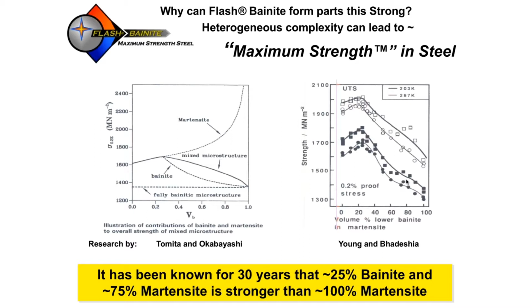Now, on this chart, the strength on the vertical axis is megapascals, of course, and on the horizontal axis is the volume fraction of bainite in a martensite matrix. So what that means is at 0% bainite, 100% martensite, this particular alloy system, shown by the darkened in circles and darkened in squares, can have a 1700 megapascal UTS. Now, if you went the other direction to 100% bainite, you would see that the strength drops down to 1400 megapascals. And bear in mind that these are medium carbon steels with heavy alloy concentrations, so you can controllably achieve the various volume fractions of bainite.